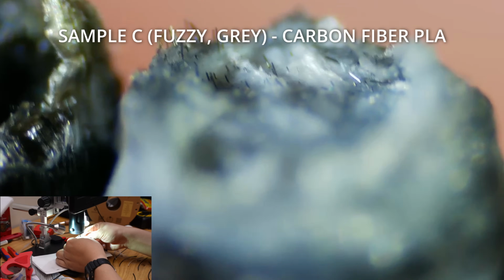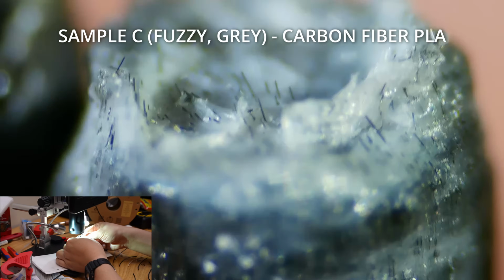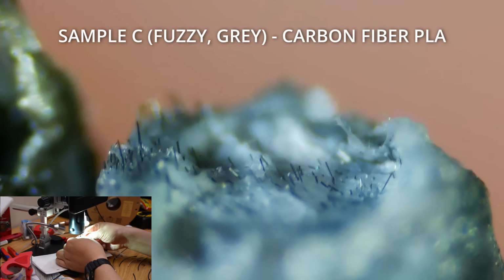This sample is from Creality. This is a Hyper PLA CF formulation. And I'm not sure what to make of the fiber sizes. They look like they're a little bit finer than what you have in this Bambu Lab PA CF stuff. So smaller fibers, and I also noticed, if we look at this edge on, there's almost no bubbles in this filament. Whereas when I was looking at the Bambu Lab stuff, there's a lot of bubbles in it.